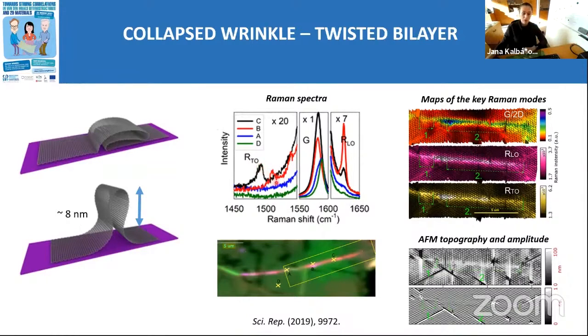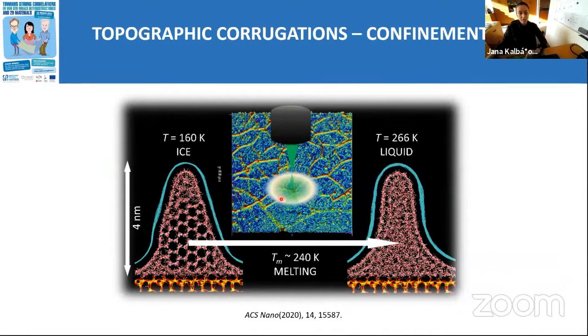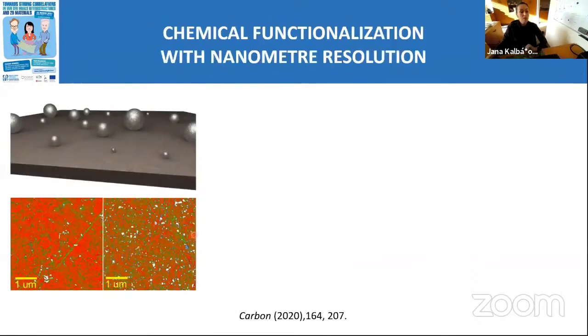And all these extra bands, coming from processes outside the Brillouin zone, are always a signature of a specific twist angle in the graphene bilayer. So by scanning along the wrinkle, we can go point by point. We can identify in every region what the twist is, depending on the excitation energy of the laser used, and also depending on the position of these extra bands, because their position is also driven by the twist angle of the graphene bilayers. So I will probably skip this slide here, and I will stay with the rugas.